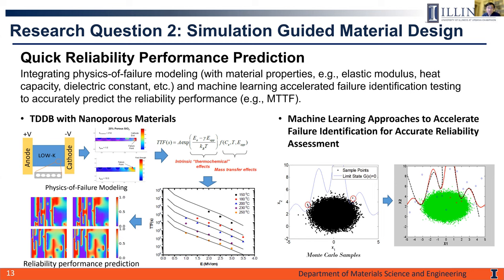reliability performance. For example, if we consider the time-dependent dielectric breakdown with the nanoporous material, we could build these physics of failure models, and then use either the field-driven or current-driven models to extrapolate to the time to failure of this material.